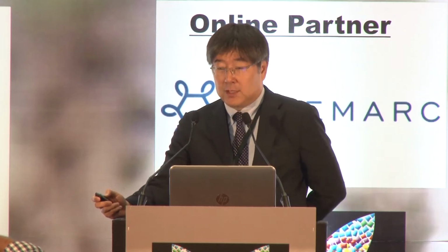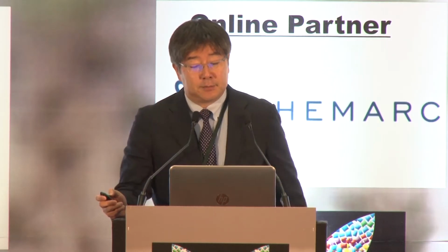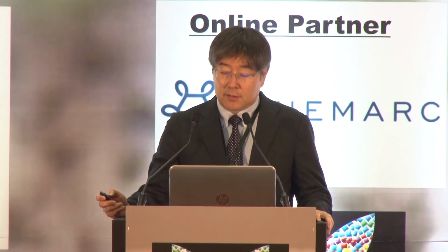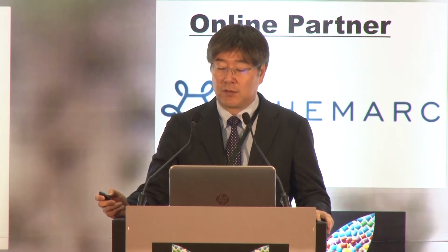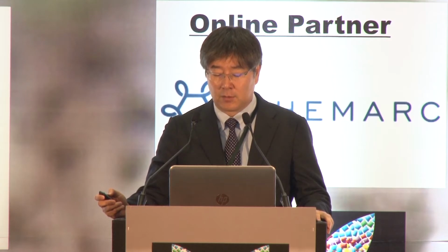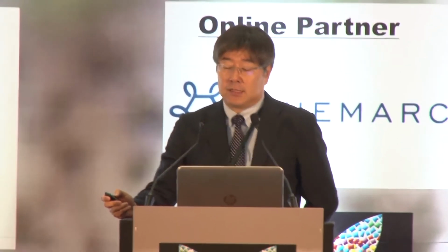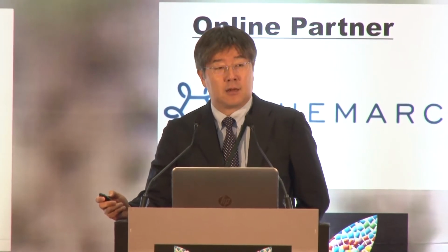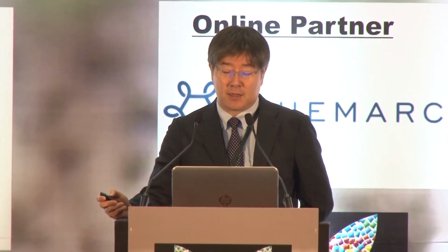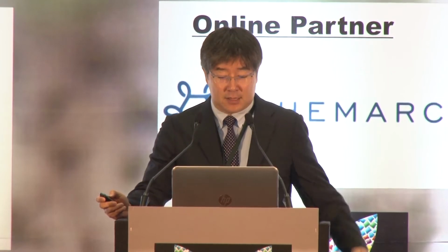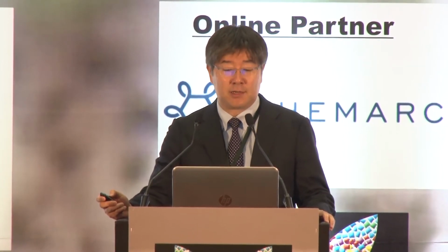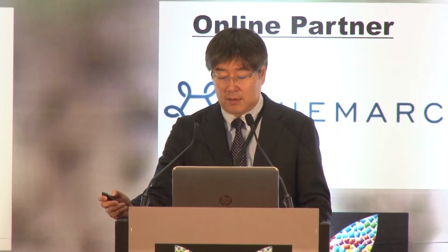Compared to the combination of reference 1 and reference 2, total 0.2 phr, 0.2% of the LA402AF can provide the same or better performance. And if you add a little more, 0.3%, you can have much better weatherability of the parts.